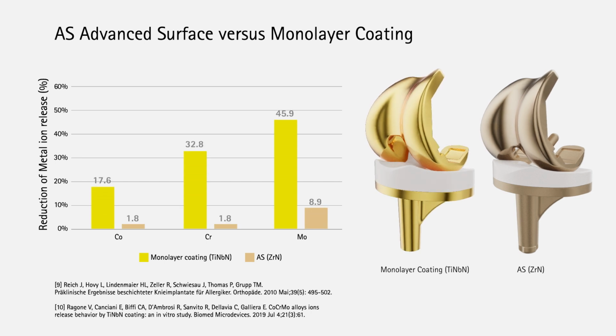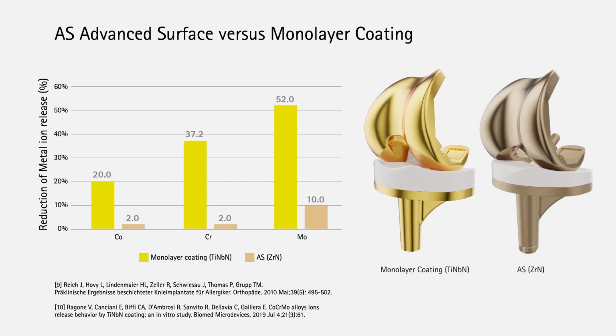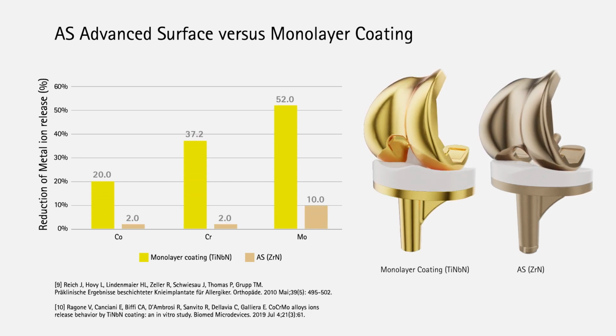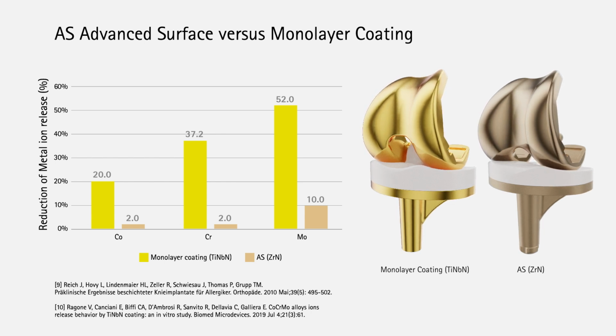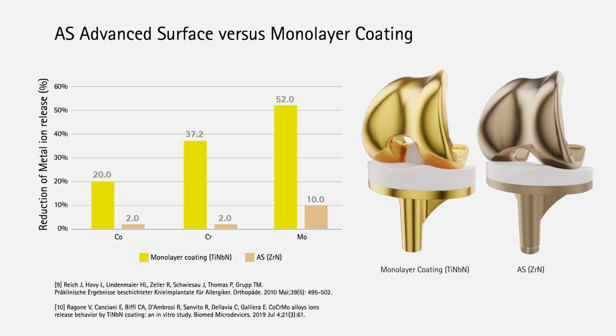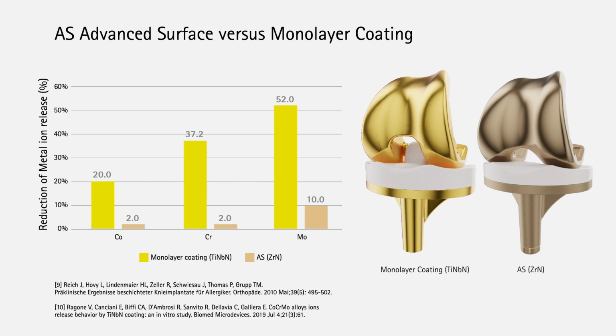Study results show that the multilayer coating is more effective in the reduction of metal ion release than the monolayer coatings. This graph shows the metal ion release of implants with AS coating in comparison with monolayer coatings. The metal ion release could be reduced to 2% for cobalt and chrome and 10% for molybdenum with the advanced surface technology.